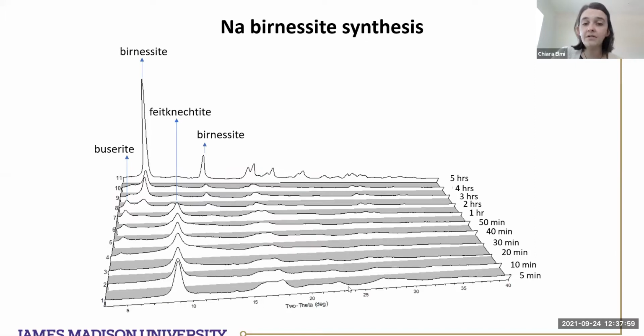So what I've done was studying the evolution of this reactivity, the evolution of the crystal growth. I selected the mineral that I was synthesizing every hour, and every 5 minutes, 10 minutes during the process. In this way I noticed the evolution of the phases and the growth of this crystal over time. The result after 5 hours of synthesis is the Birnessite, the phyllomanganate that I need for my experiment.